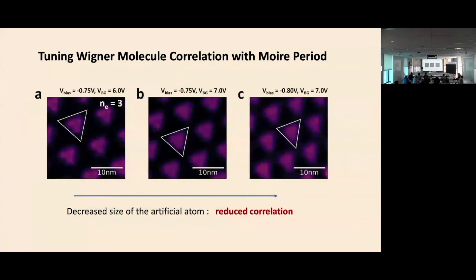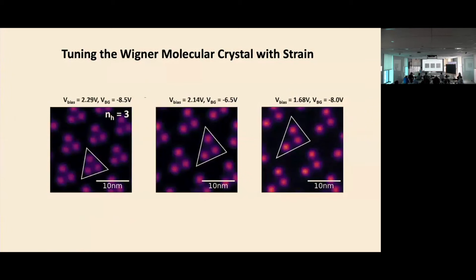When you change the Moiré period a little bit, for a larger period you can see pretty well-defined three dots; for smaller period it becomes harder to distinguish, as the competition between potential and kinetic energy changes. In many systems there are random strains that can dramatically change the configuration. The anisotropy you see is largely due to residue strain distorting the nearby region. It would be interesting to ask whether, with truly no strain, there would be some spontaneous nematic-type order — but this has not been distinguished yet because the inter-molecular interaction is still pretty strong.